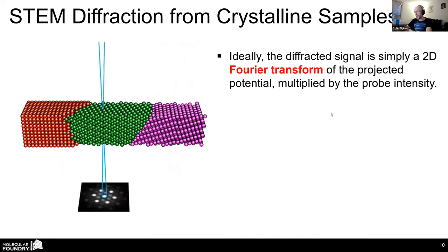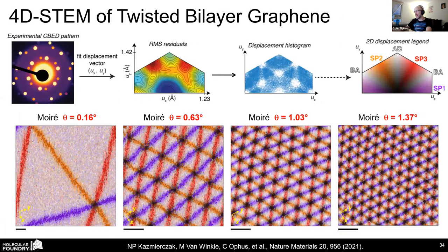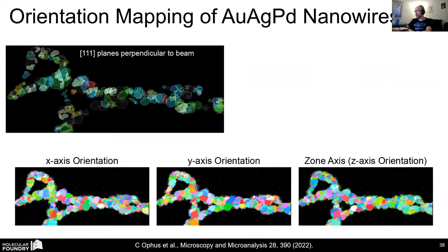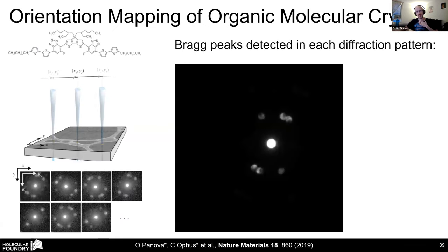So pulling ahead to the orientation mapping here, this convergent semi-angle is about 0.25 milliradians. So we're talking about very, very small scattering vectors. We've since machined our own apertures that we give away for free to anybody with an electron microscope that go down to 0.1 milliradians using standard microscope settings. That would form a probe in real space somewhere in the ballpark of 5 nanometers. So what I'm really getting at to answer your question is we tune it to the experiment at hand.